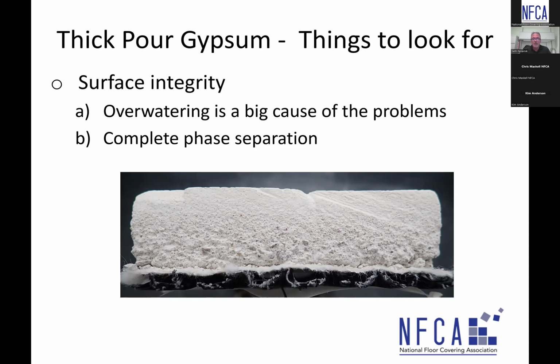Okay. Looking at the cross section of any type of pourable product like this, we should see sand top, middle, and bottom. And you can see that with the naked eye. And if you're having trouble, you can just get like a little 10 power magnifying glass and look at the cross section and see that the sand is evenly distributed top, middle, bottom. But anytime there's a concern, even with self-leveling underlayments, get the manufacturer involved to let them evaluate their material and confirm the cause for the condition and make a recommendation for remediation.